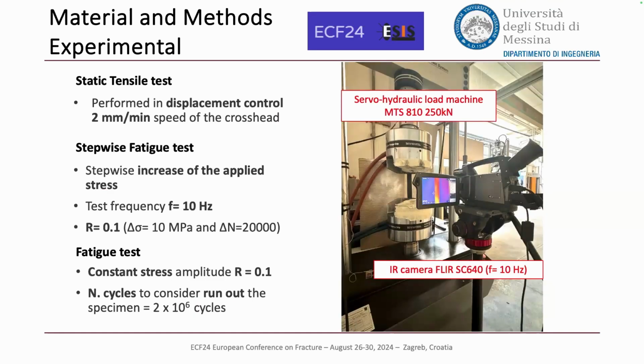For the experimentation, we use a servo-hydraulic load machine of 250 kilonewton. And in order to monitor the thermal behavior on the specimen surface, we use the infrared camera of FLIR. We carried out 3 types of tests. The static tensile test performed in displacement control at 2 mm per minute. The stepwise fatigue test, and the classic fatigue test, so in constant stress amplitude with a load ratio of 0.1.